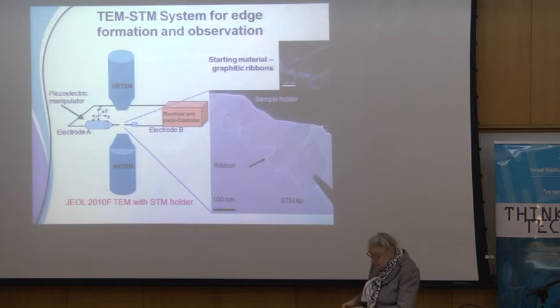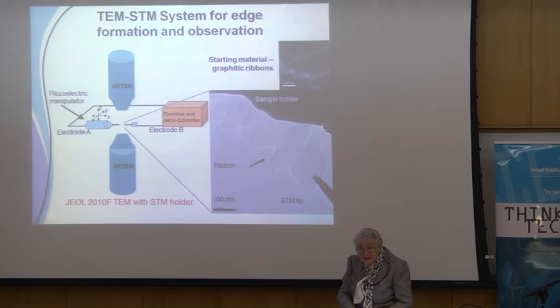So the ribbon that we work with, here's a graphene ribbon. And this is the plane of graphene. And the ribbon comes like this, it's all rolled up. And then we could put electrodes across like this and heat it up. You put an electrode on top of one side and the bottom of the other side, and you get a high resistance. So it gets very hot. It goes up to approximately 2,000 degrees.